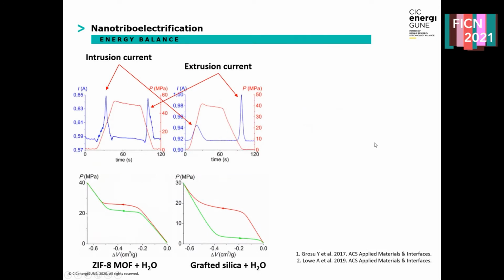But independently of the configuration, we were able to record a pronounced current exactly at the intrusion-extrusion pressures. As you can see, these peaks of the generated current have the same sign during intrusion and extrusion. The reason is that we are recording the current for the macroscopic system, so basically for the suspension of the particles in the liquid, and they seem to become equally charged both during intrusion and extrusion, so during the displacement of water inside the pores.